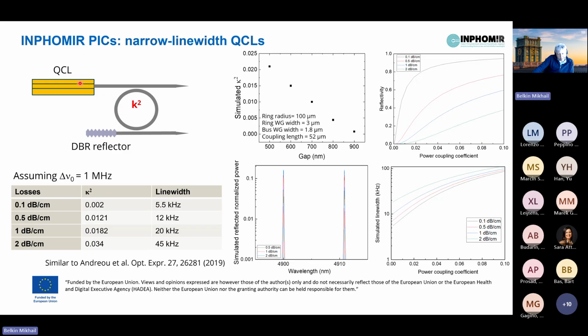The way we implement our narrow linewidth PIC is shown here. We have a ring resonator critically coupled to the bus waveguide that is then tapered to avoid any feedback, and then a strong DBR reflector to reflect the light coupled to this bus waveguide and couple it back to the laser. Our calculations, following the formalism that is already introduced in this reference for the near-infrared lasers, predict that with reasonable losses in our waveguides, let's say half dB per centimeter, we could reduce the linewidth of a free running QCL from 1 megahertz down to maybe as low as 10-20 kilohertz. And these are some simulation results for the feedback spacing determined by the ring resonator radius and for the linewidths as a function of coupling coefficient between the bus and the ring.